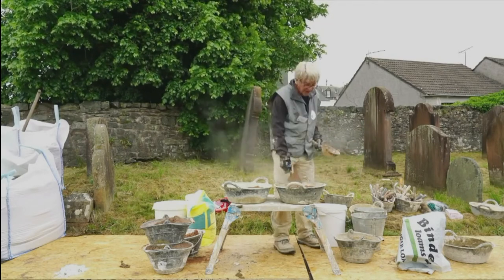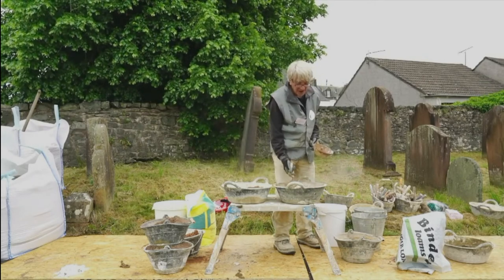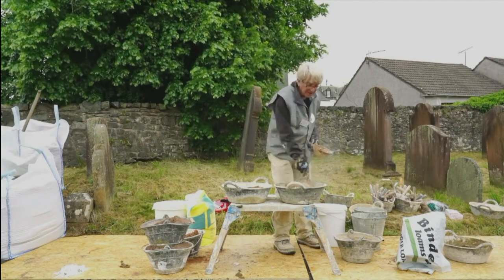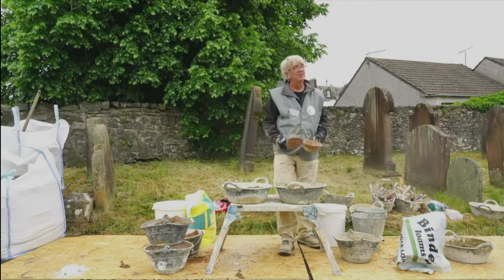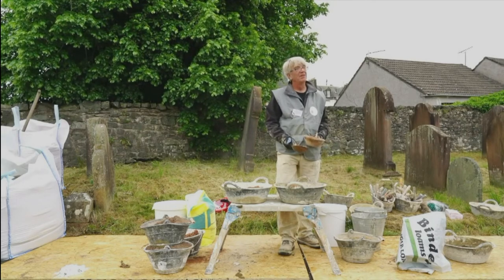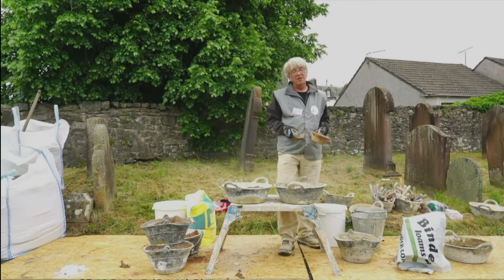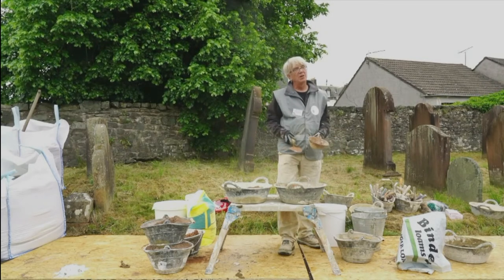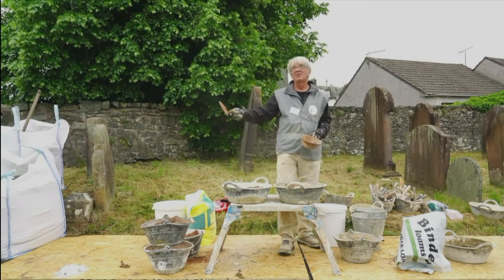Now, they'd love that historically, because you'll see it constantly, and this is where it's obvious they're not talking about hydraulic lime: the lime which slakes the fastest and the hottest is the best. The only lime that will slake straight away is pure lime. So with hydraulic lime, depending how hydraulic it is, we could do this and we'd still be looking at it 12 hours later waiting for something to happen. That's the difference. It doesn't slake very fast at all.